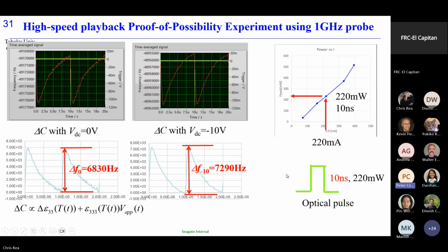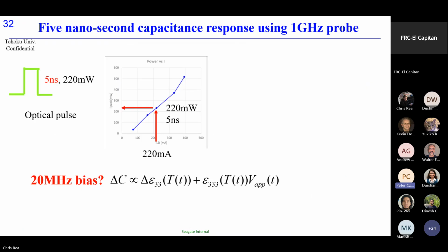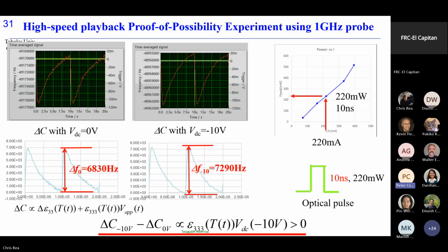So this is the output of the linear capacitance response, and this is the frequency change. And when we apply a DC bias voltage, in this case minus 10 volt, a little bit larger frequency change was detected.